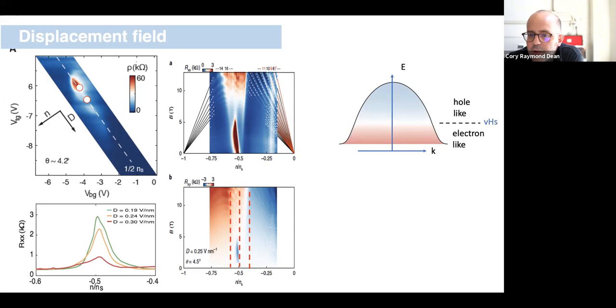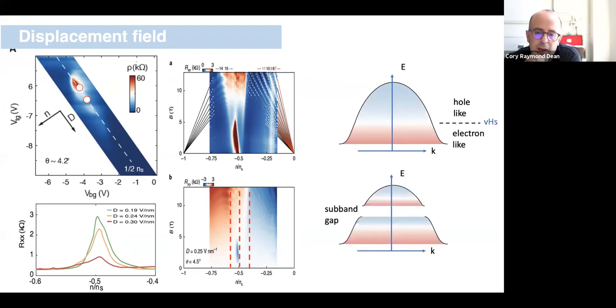And if I measure Hall effect, as I dope through that Van Hove singularity, I expect the sign of the Hall to change. It will change from having a hole-like sign to the electron-like sign. In a scenario where I take this single particle band and I introduce some subband gap for some reason, perhaps we have an interaction-driven insulating state, for example, then necessarily what you might expect is that I have to inflect the sign of the carrier through the band more than once. And indeed, you can identify that you would expect it to happen really 3 times.